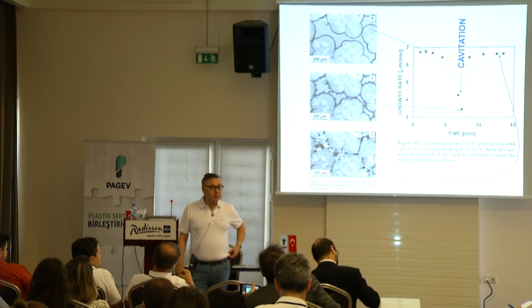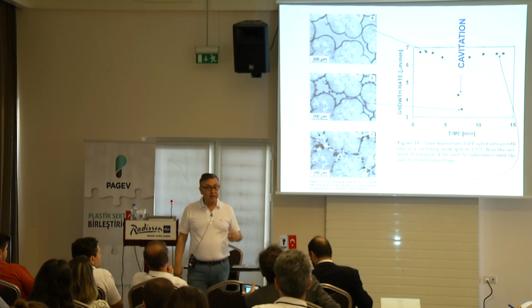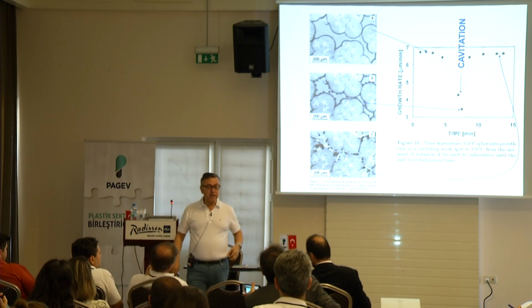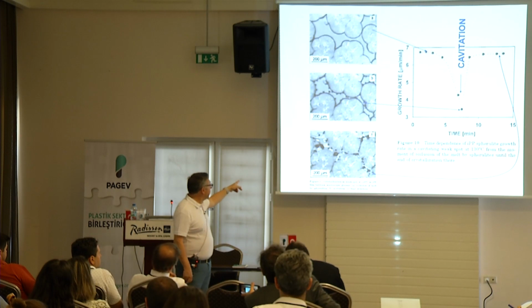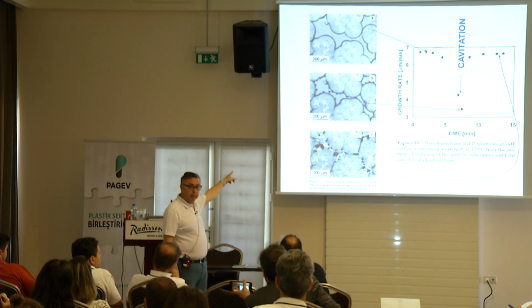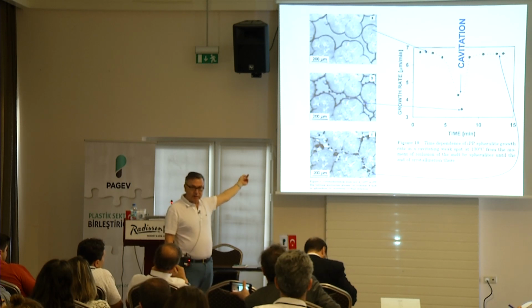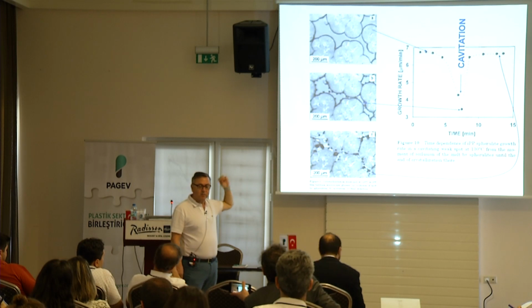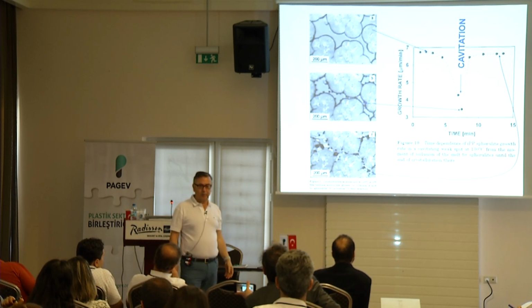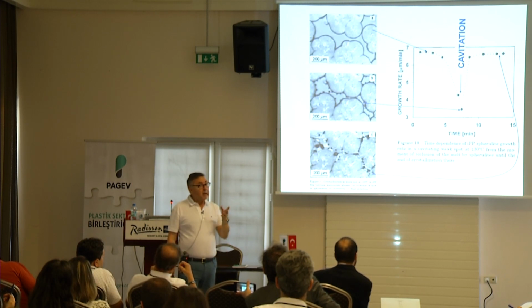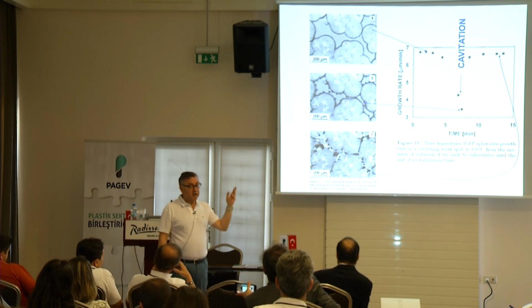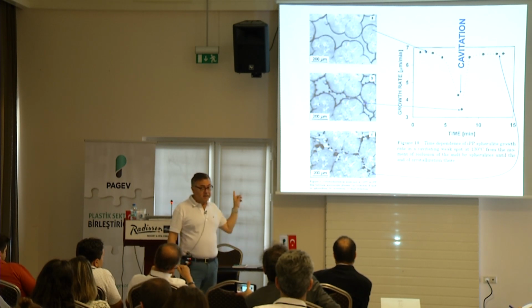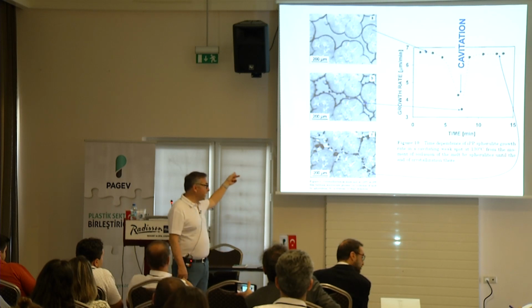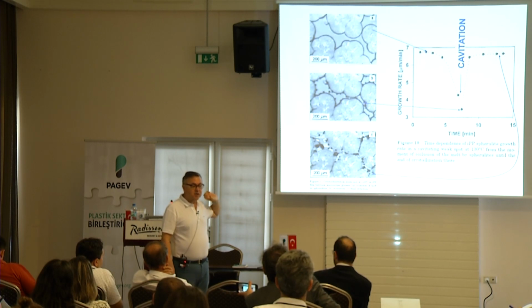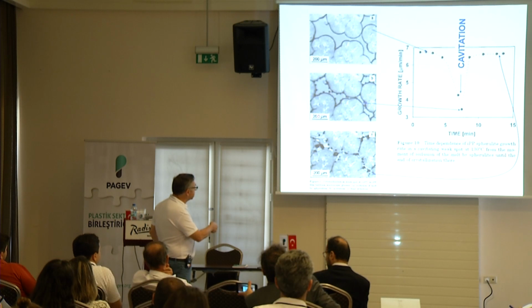Excellent question. I suppose when you have smaller spherulite sizes, the confinement may not be as bad. It's much more homogeneous, so you may not see these. Look at the size of the spherulites in this case, 200 micrometers. You don't see that in industry. I think this is an exaggeration because they're almost like homogeneous nucleation. Almost all polypropylenes are sold with nucleating agents. People may not see it in normal conditions because you have such a large amount of crystals. But it may still be there if you look for it. This is an exaggerated experiment. I just wanted to put it out there for people to see. These are gigantic crystals, 200 microns. It's huge, the crystals.